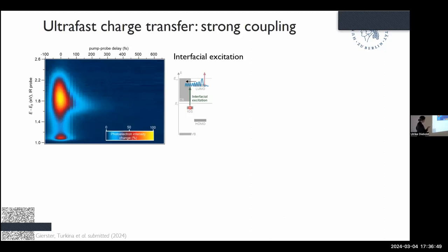This is again photoelectron intensity as a function of energy, again with respect to the Fermi energy, and as a function of pump-probe delay. But now we are looking at the normally unoccupied states. So this feature here lies at 1.8 eV above the Fermi energy. Before we've been looking in this region, now we look up here. And the signal that you see here is the transient population in the LUMO that then very quickly decays on femtosecond timescales. It decays with a time constant of 70 femtoseconds, so this is really ultrafast. This means that the density of states argument really cannot be true. The electrons go away into the conduction band of the zinc oxide very, very quickly. So we have to have strong electronic coupling and sufficient density of states.